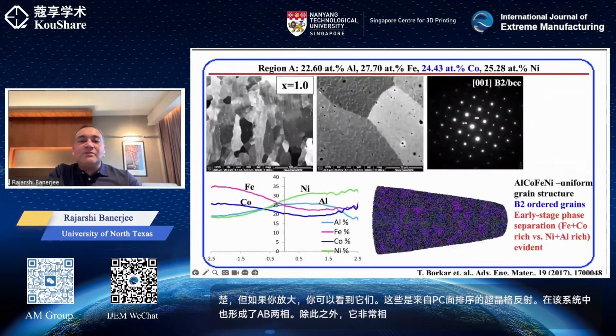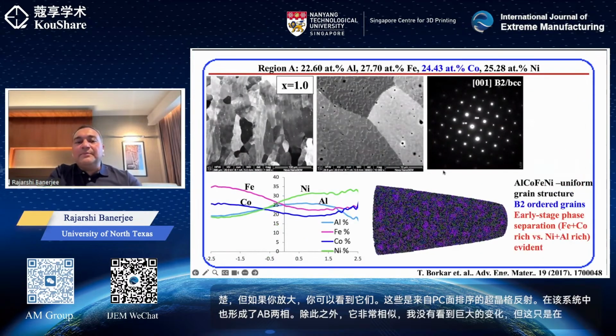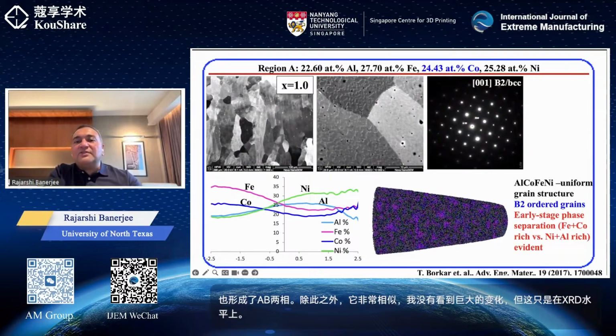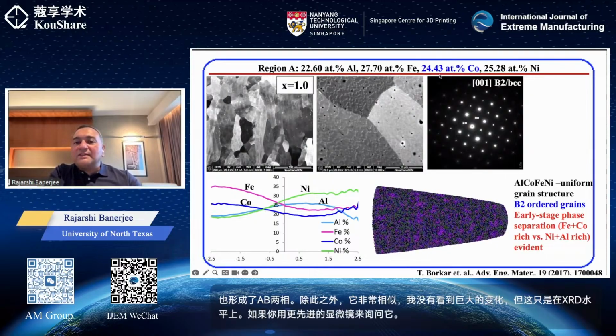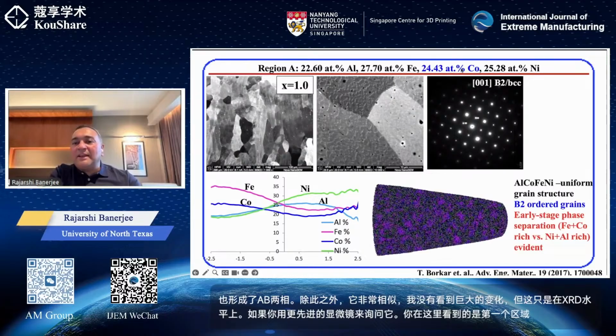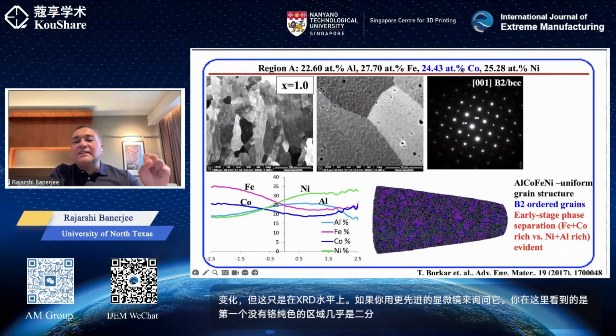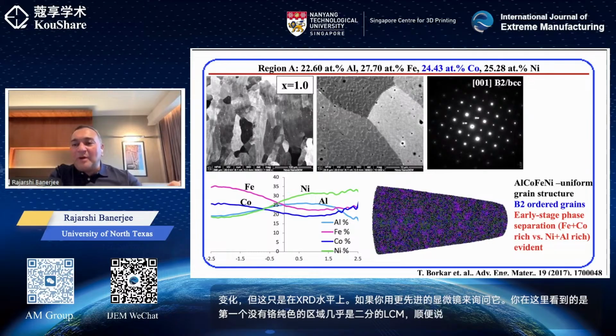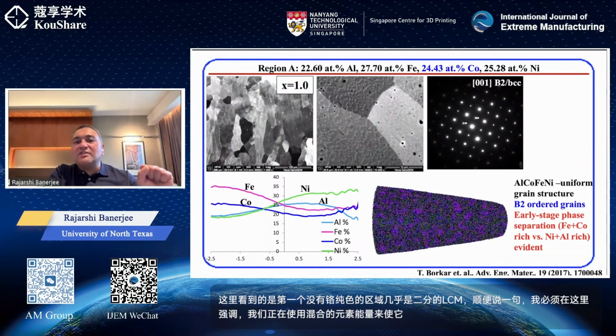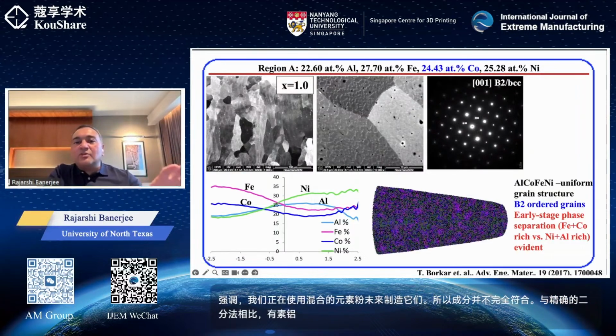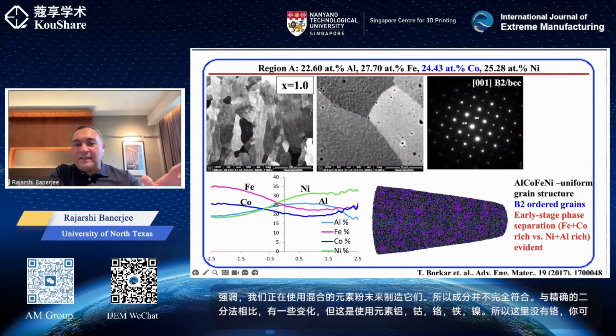If you interrogate it using more advanced microscopy, what you see here is the first region, which has no chromium, pure cobalt, almost equiatomic AlCoFeNi. By the way, I must re-emphasize that we are using blended elemental powders for making them, so the compositions are not exactly dead on. There are some changes from the exact equiatomic, but this is using elemental aluminum, cobalt, iron, and nickel. So here there is no chromium. You can see this is pretty much B2, as the electron diffraction pattern shows you. They look like large grains of a single phase.